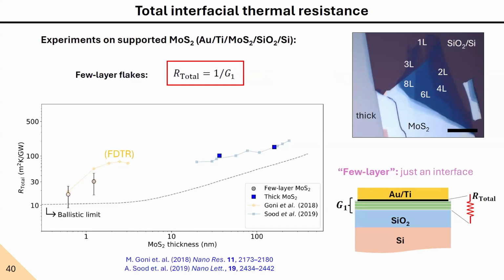For the very thin flakes, the heat transport within the flake is not so relevant. It is all dominated by the interfacial resistance, the conductance between our transducer and our substrate. In any case, our flakes agree very well with available literature. They are very close to the ballistic limit. The offset is the effect of the interfaces.